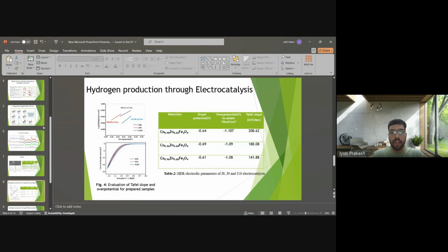For hydrogen production through electrocatalysis, we studied the Tafel slope and also studied the potential with current density to check whether it is electrocatalytically active or not. For our sample, it was found that with increment of dopant, the value of Tafel slope goes on decreasing, which is a result we require because a low Tafel slope shows that it requires lower overpotential to achieve the electrocatalysis, and it also shows a faster electrocatalytic reaction, making it suitable for hydrogen production through electrocatalysis.